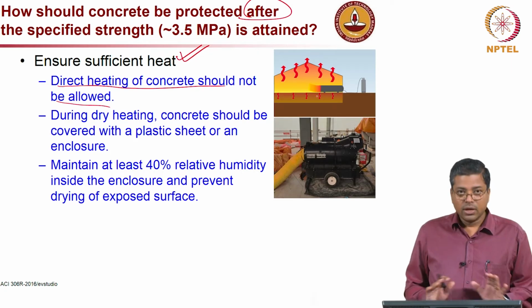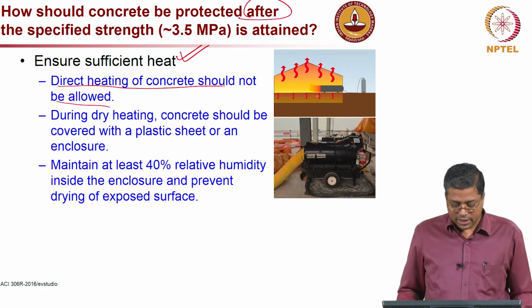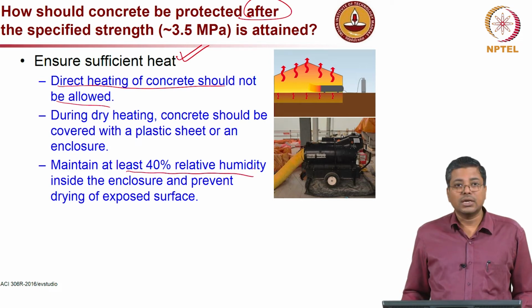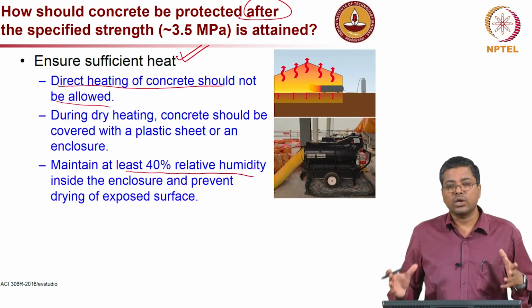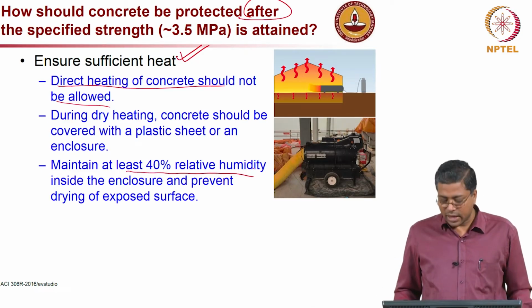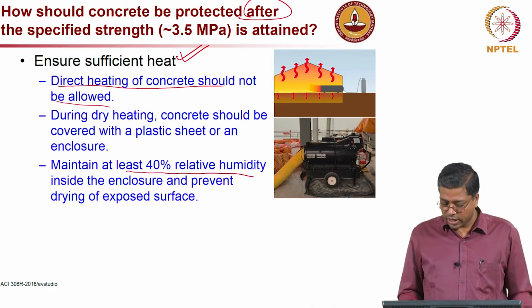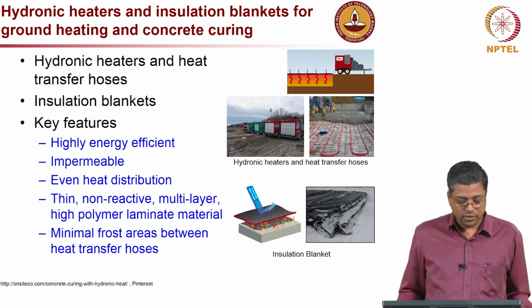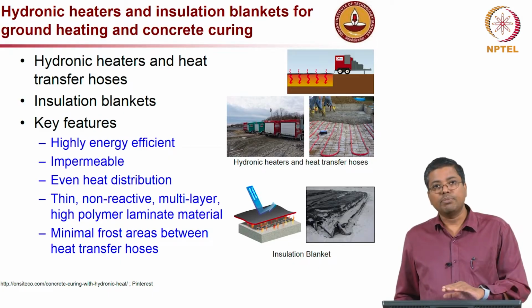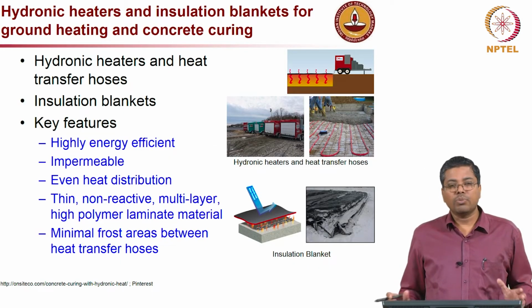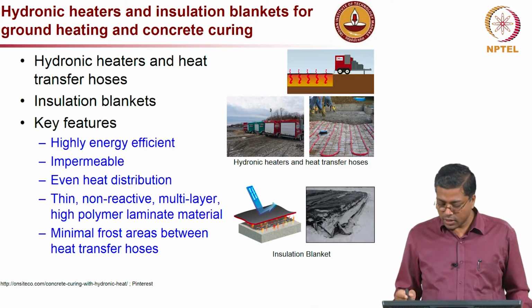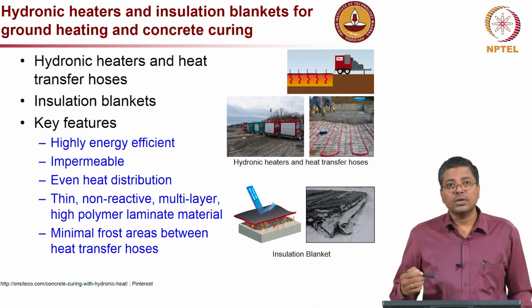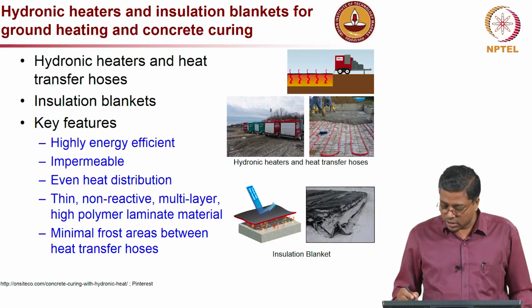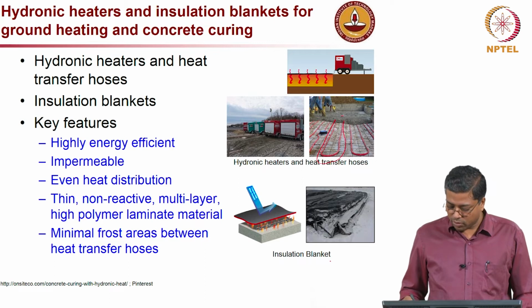So, the uniform heating is essential, not direct heating or localized heating, and maintain at least 40% relative humidity inside the enclosure, because if you keep it too dry, then concrete will dry and it will not have enough moisture for hydration to happen, especially near the surface. The other way is by keeping the environment hot or providing external heat by using hydronic heaters or these heat transfer hoses which you see, and also by providing a blanket.